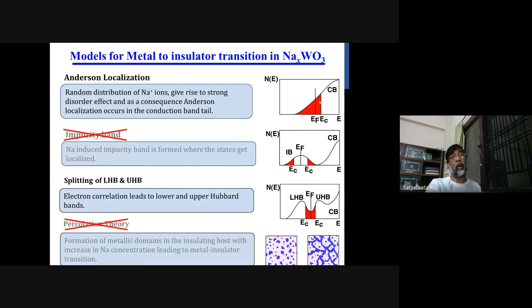You have a critical edge of the doping, and below the mobility edge all these states are localized, and these are non-localized states. EF can move from WO3 slowly with the sodium electron doping, and as soon as it crosses your mobility edge, you are seeing metallicity in the sample. But this Anderson localization can have a lot of consequences, and let's see what the consequences are.